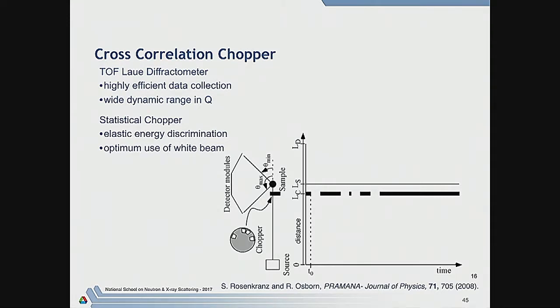But instead of a single disk chopper or a Fermi chopper, we put in a chopper which has a whole set of apertures in it in some kind of a sequence. Which is apparently random. So imagine you have a disk, and there are, in principle, 256 slots on that disk where you could put an aperture. And you put an aperture in 128 of those slots, but not in any sort of regular sequence. You put them in some kind of a random, or apparently random, sequence. It can't be exactly random. It's called pseudo-random. But nevertheless, you put apertures in 128 slots, or alternatively, you paint absorbing paint over the other 128. So you only let neutrons through at certain times.